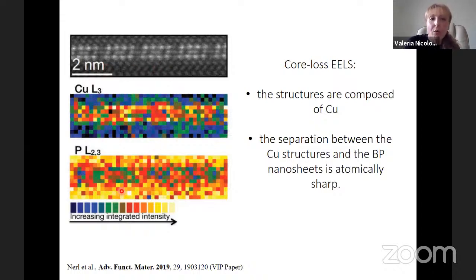There was no phosphorus, well, it was phosphorus all around. So it was a phosphorus sheet with no oxygen at all, not oxidized. And we could track this by being made of copper. So it was really the copper diffusing along the structure and creating these very ordered anisotropic structures.